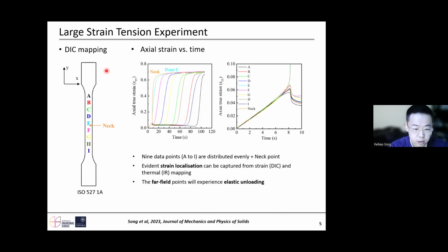Here is the digital image correlation mapping. I put 9 data points in the gauge section and another data point called neck. It means the neck occurred in this area first. And if we see the axial true strain versus time curve, here is a zoomed-in image. We can see the data point called neck, or data points quite close to the neck, just go up directly.